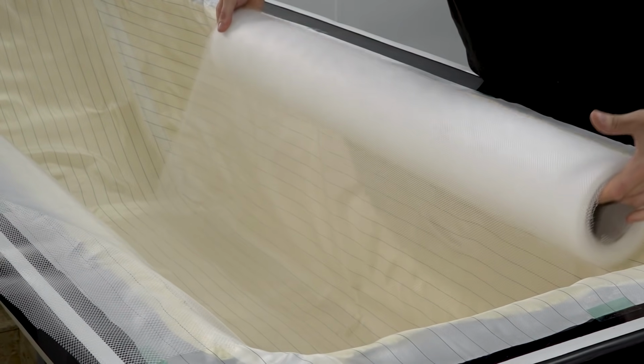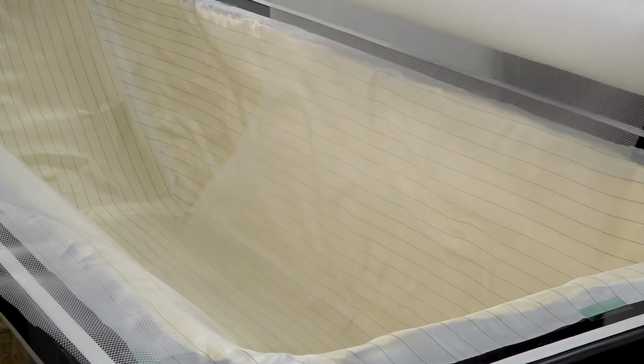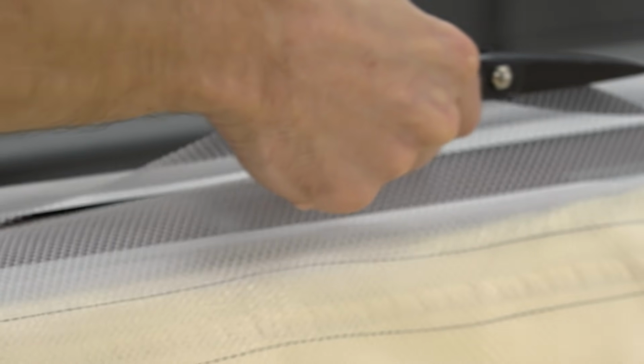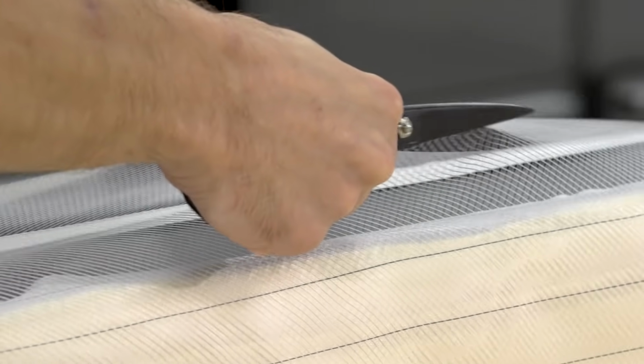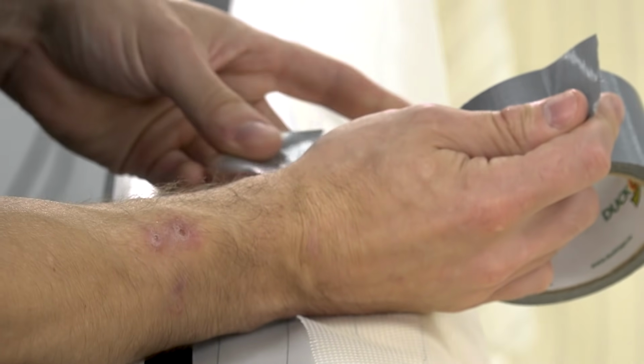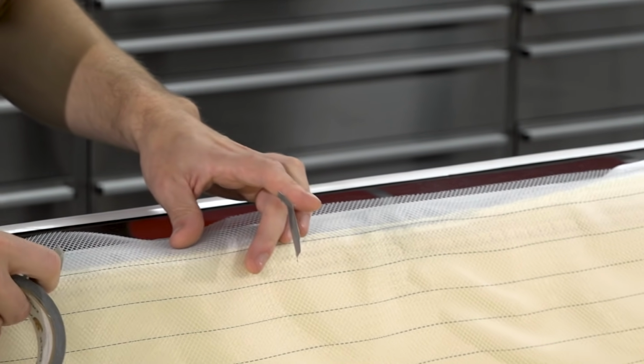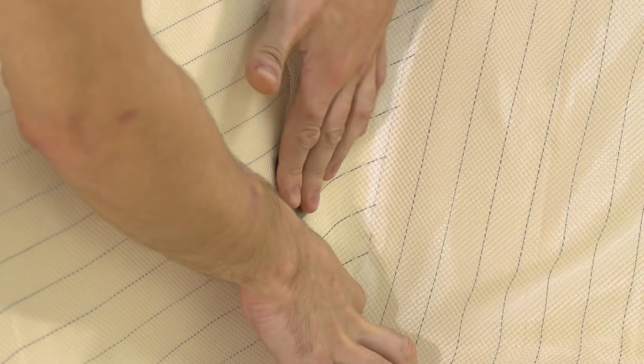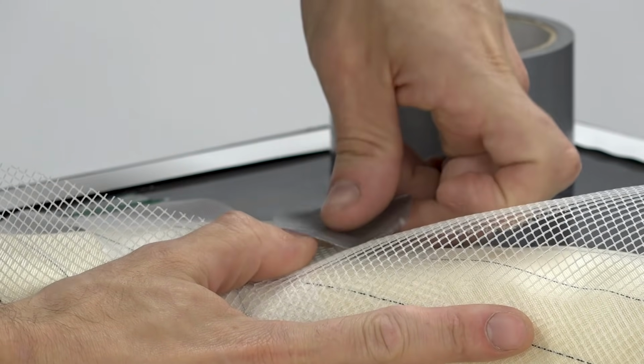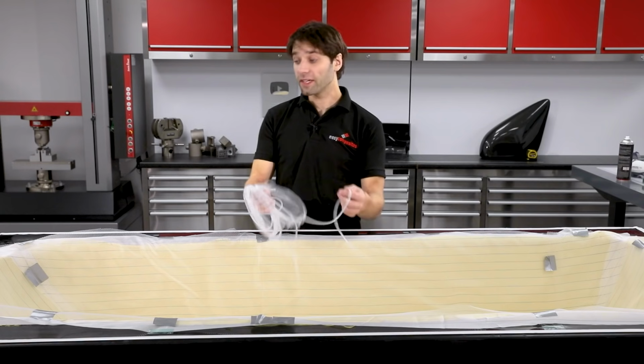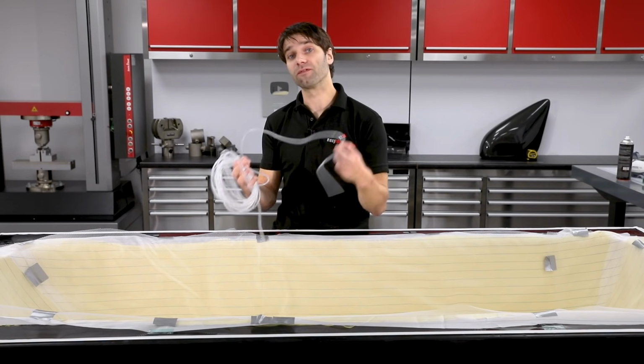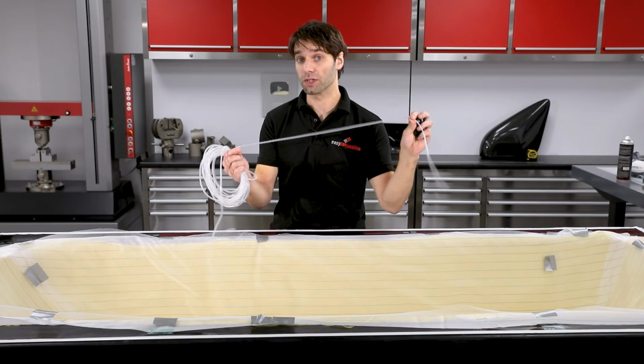The mesh can now be placed. This should be sized slightly smaller than the peel ply. Spray tack doesn't hold this, and even the flash release tape doesn't tack it very well. However, duct tape adheres adequately, so small tabs should be used to secure it in place. As these tabs are on the back of the mesh, they will have no influence on the infusion going on underneath. We now need to consider where we're going to position the resin feed lines, vacuum points and distribution spiral.